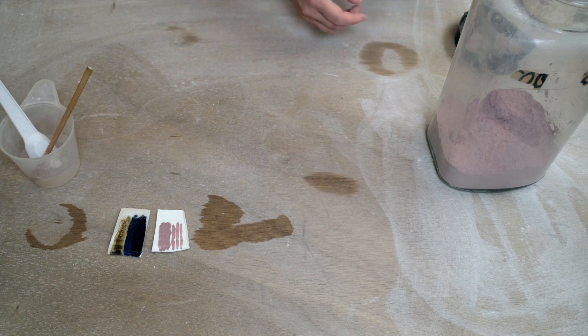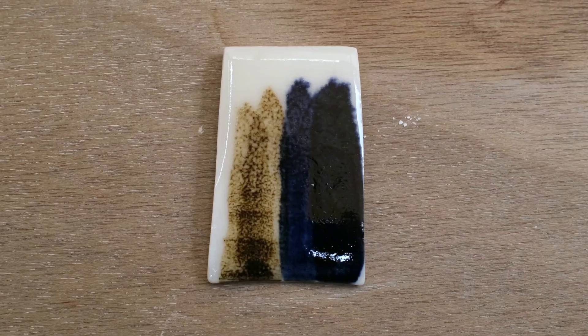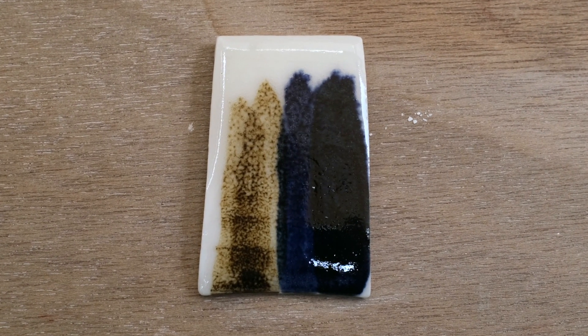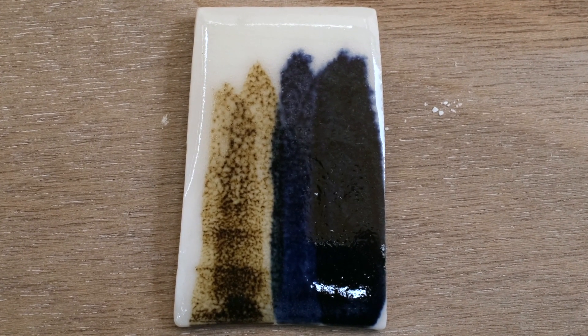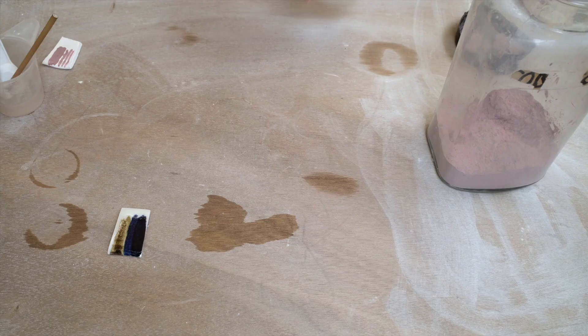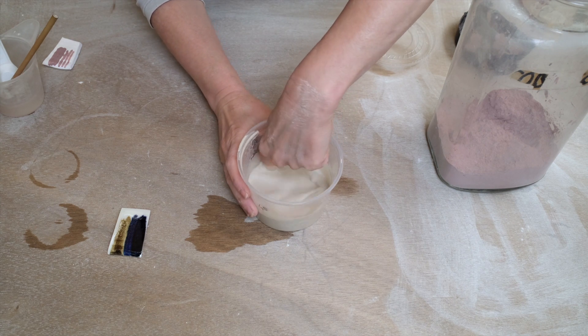This is an example of one I've fired already. This one has iron oxide brushed on the left hand side and cobalt oxide brushed on the right hand side. You can see where it's thicker the cobalt oxides come out darker. You can see the pink carbonate has changed to a really strong blue colour. So now we're going to dip our test tile into the clear cone 8 glaze that we made in the last video.